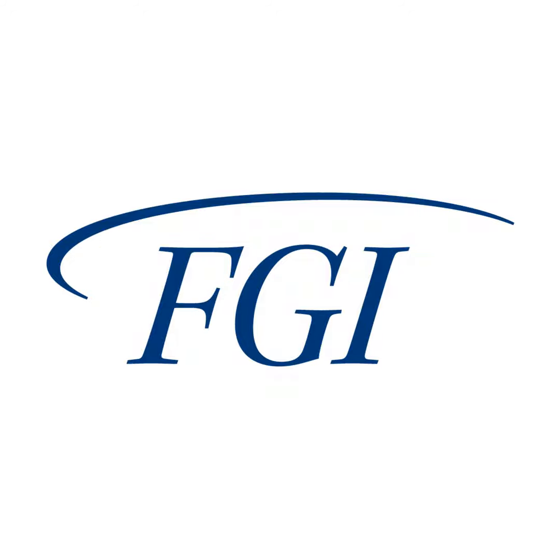And the really good thing is that you can do that for an actual service temperature, which is not the case for the basic creep test. With the SIM test, you can say, okay, the temperature of service is going to be 35 Celsius. So let's see what is going to be the residual thickness after 100 years at 35 Celsius. So you can play with these numbers. It's really extremely performant to assess very long-term properties of drainage geocomposites.